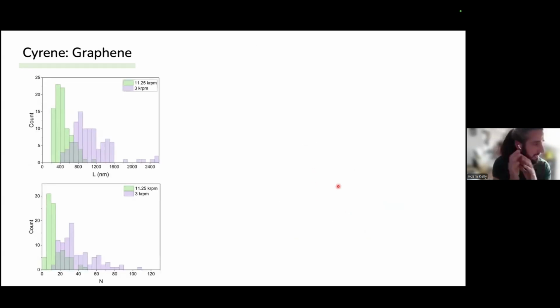So once again, we did AFM statistics on the various centrifugation speeds. This is just 2 examples here. So the low speed, 3K RPM, we see a wide distribution in nanosheet lengths. And at the high speed centrifugation, we see a very narrow distribution in length. If we look at the layer number as well, that's n layer number here, wide distribution in layer numbers at low speeds, and a very narrow distribution of layer number at high speeds.